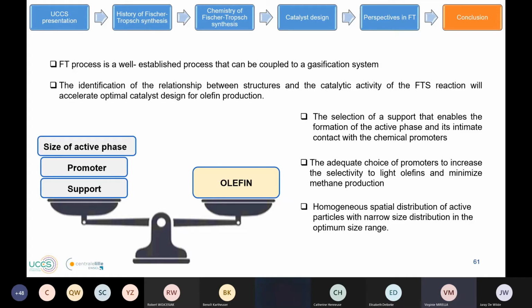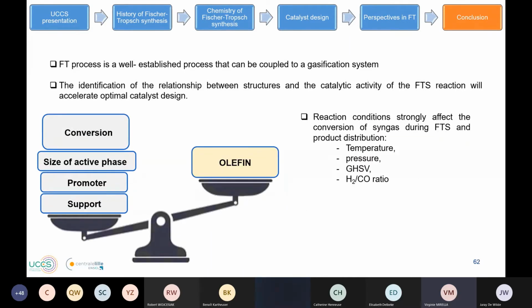We also have to pay attention to the size of the active phase. When we have too small particles, we probably don't get high olefin selectivity. So we have to pay attention to the size of the particle, but also to the dispersion of these particles on the support. And then we also have to pay attention to the reaction conditions.